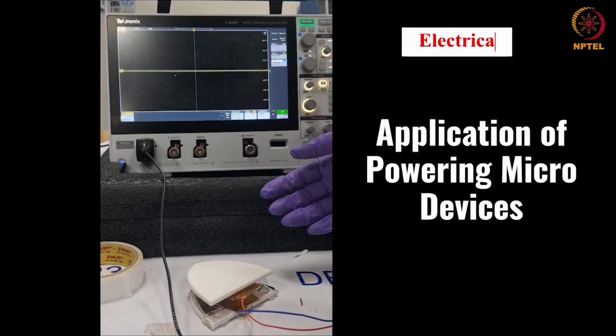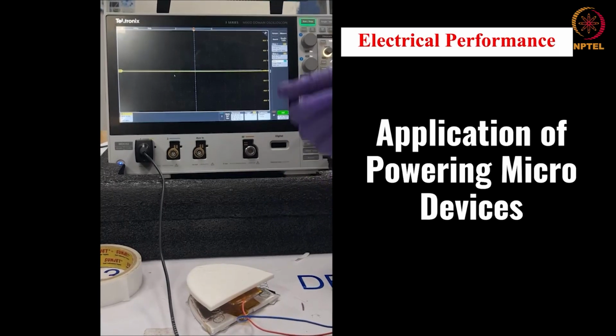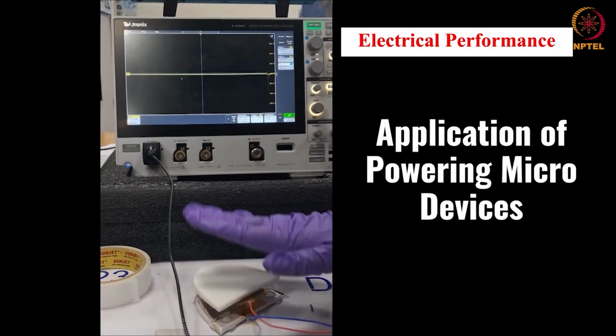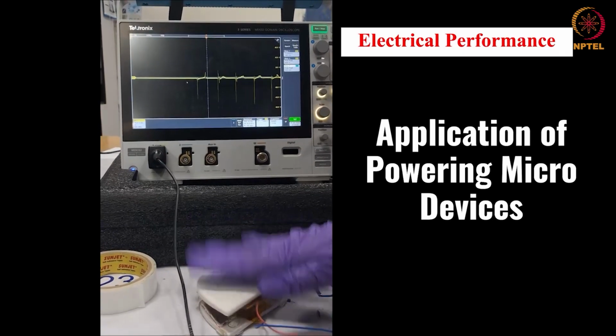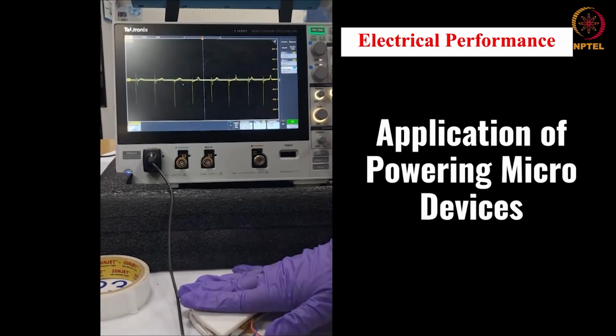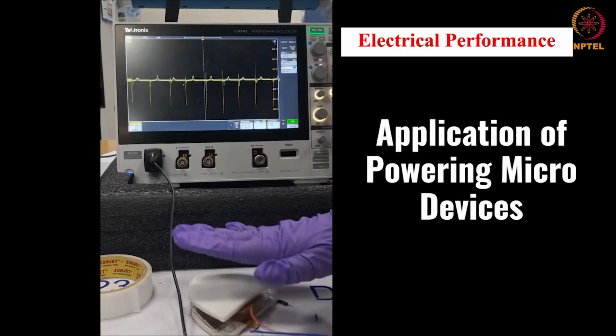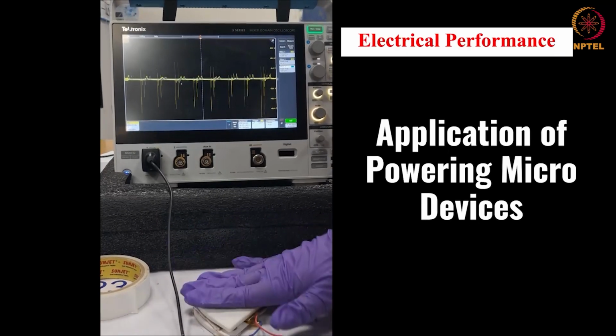To test the fabricated triboelectric nanogenerator, we connected it with an oscilloscope. By repeated contact and separation, we can see we are getting AC voltage peaks of 99 volts peak to peak.